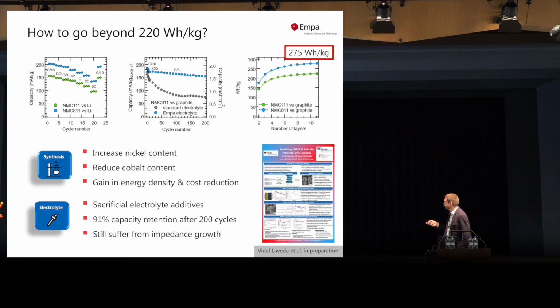You can see here the gravimetric charge capacity again for NMC 111, where nickel, manganese, and cobalt are in a ratio of 1 to 1 to 1, so about 30% each. And we are now increasing the nickel content to 80%. This has the advantage that we are increasing the charge capacity quite significantly, by about 30%. At the same time, we are reducing the cobalt content.